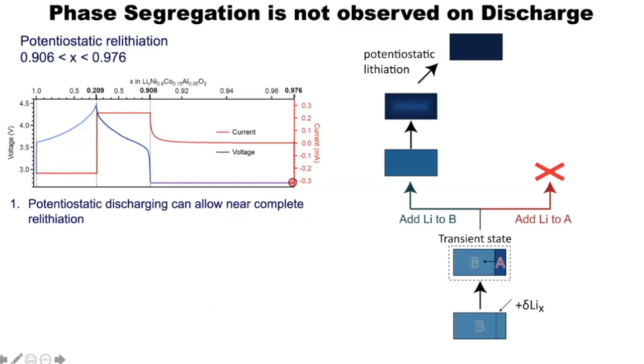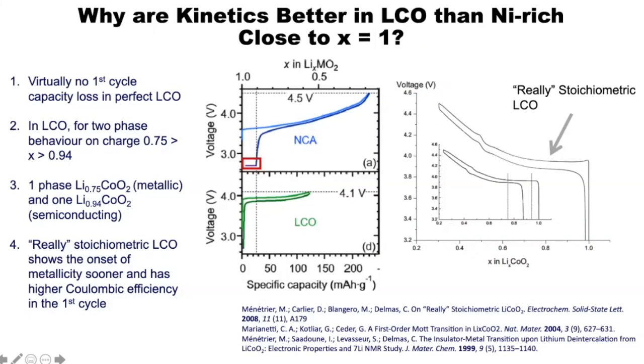And only by holding at this low voltage can you force the lithiums into this fully stuffed phase. And so using these arguments, it's very straightforward to rationalize why on charge you get two phase, on discharge you get these single phase behaviors. So then I wanted to return very briefly back to why the kinetics are, or why there's a difference in